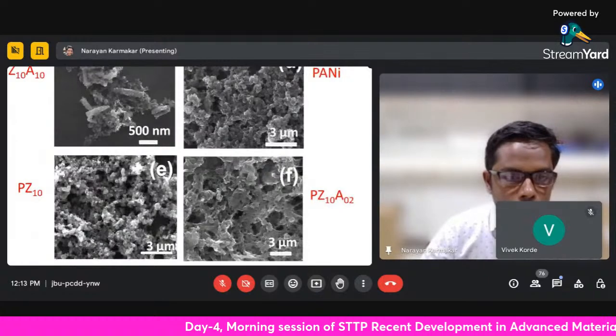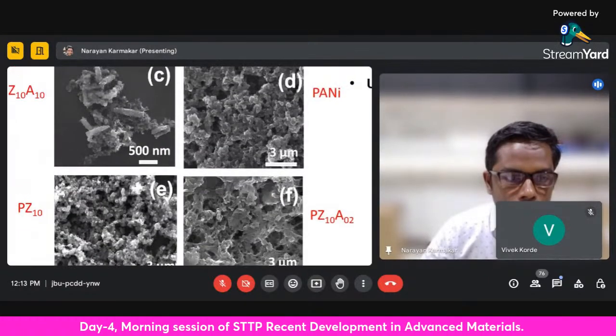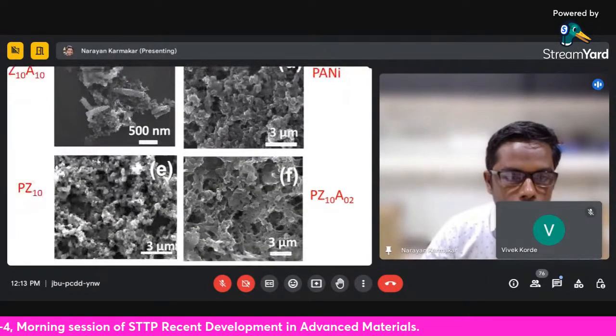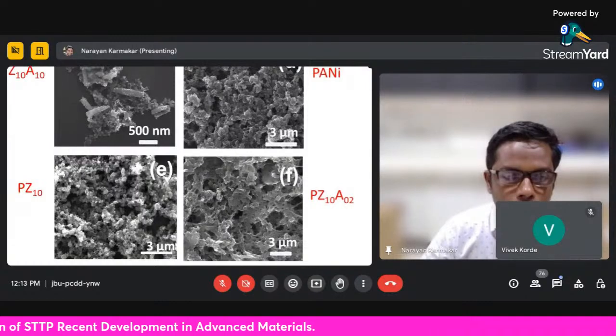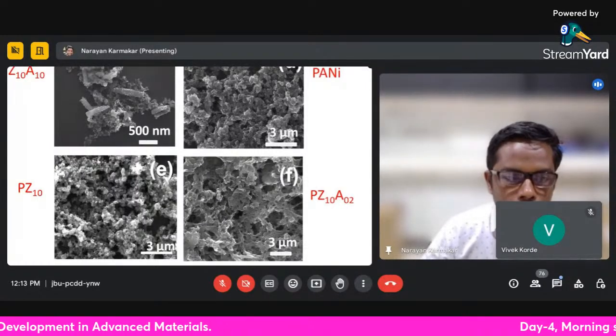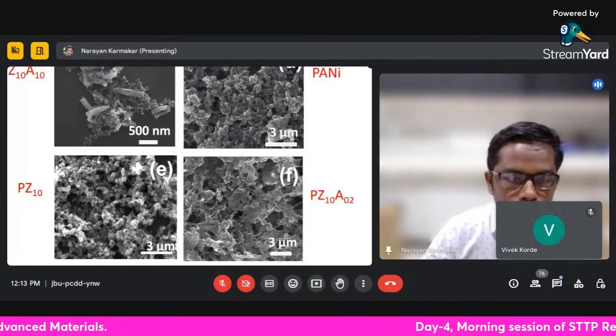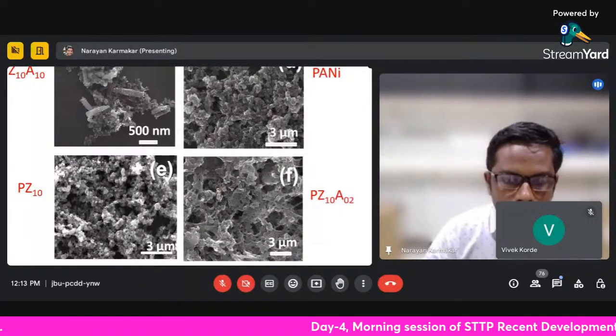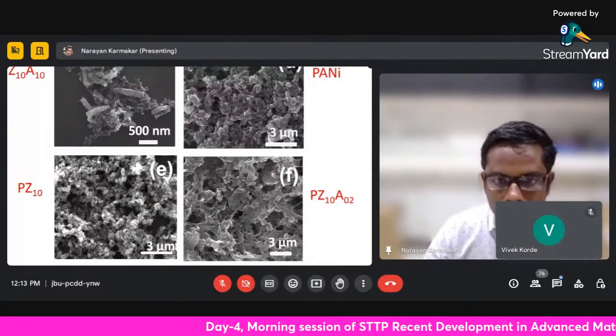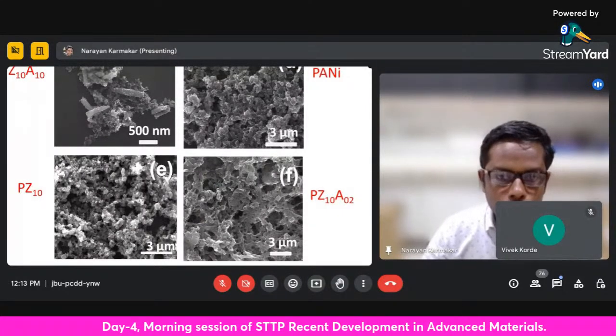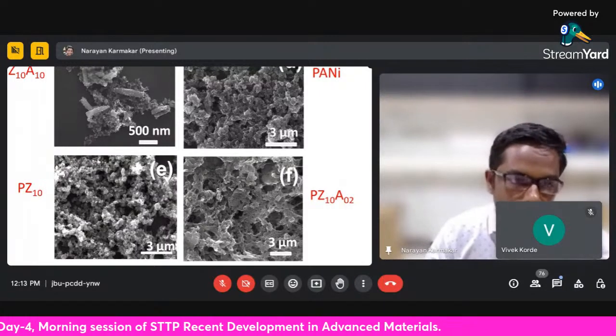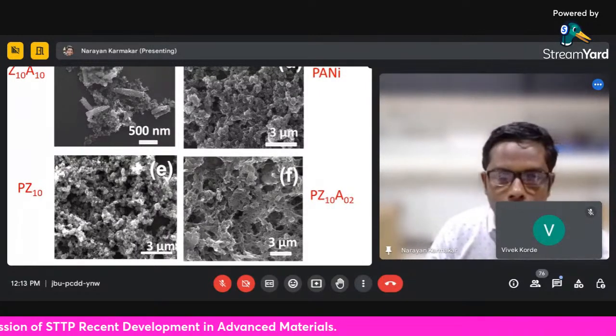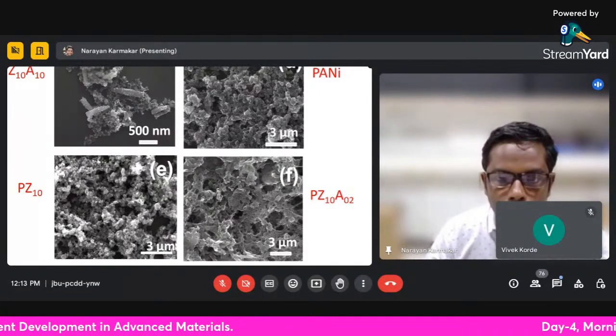This is for the PZ10 and PZ10A2. Look at this: when we form the final composite, that is PZ10A2, we can see that the structure is well defined and also porous, which is the requirement for this gas sensor. The more porous structure is often seen in this case, and because of that, the sensor was having good response to the ammonia gas.